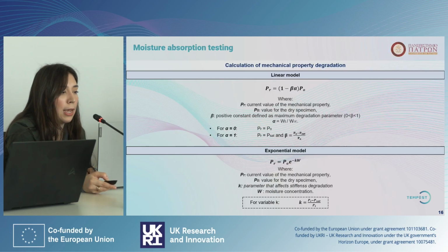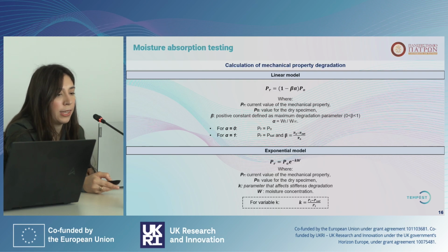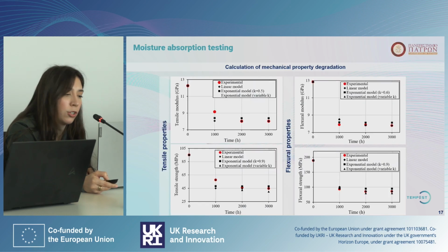Now, two models based on analytical solutions that predict the degradation of the composite's mechanical properties were used to provide predictive capability outside experimental observation. So here we have a linear and an exponential model that were used. And we see that the analytical models effectively estimate both strength and modulus, particularly at saturation, which occurs after 2,000 hours.